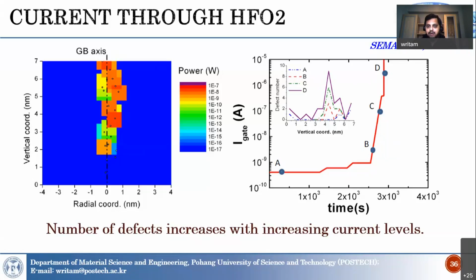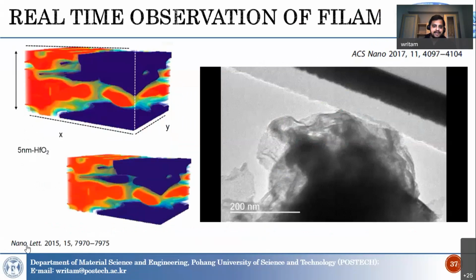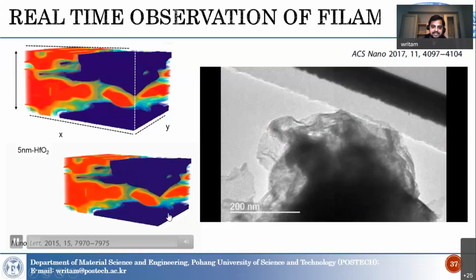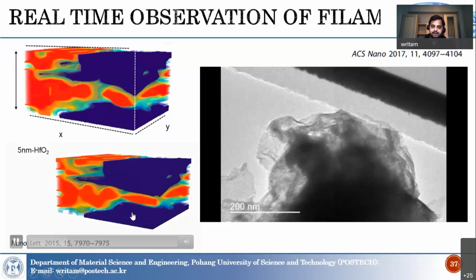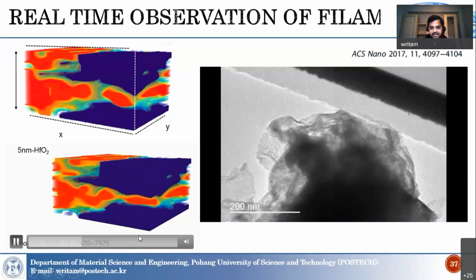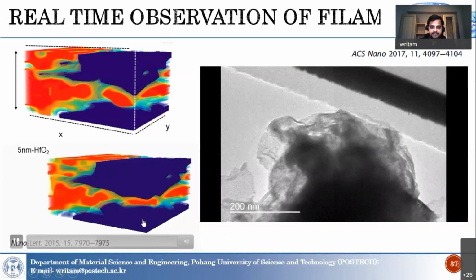So this is how when we use higher current, we introduce more defects, and the switching transforms from threshold to memory switching. And here is a nice example of how you can visualize those kind of filaments. This is a scalpel AFM image, and you can see this is the hafnium oxide, 5 nanometer hafnium oxide stack, and this is the copper layer below, and how it can form the filament.